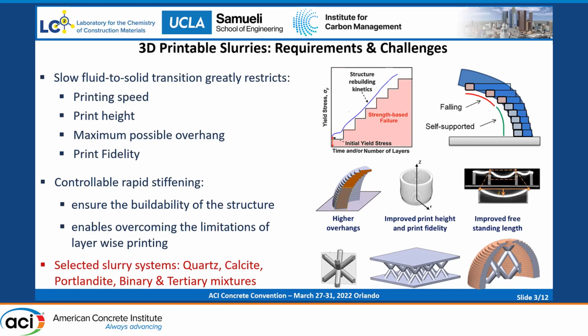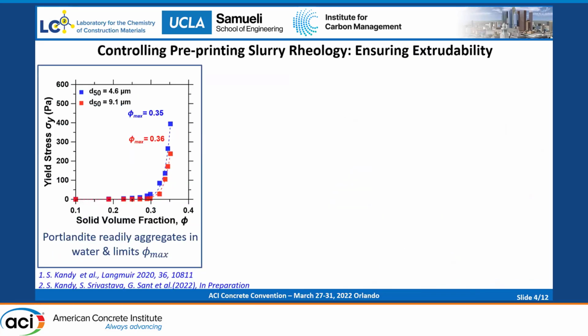We demonstrated it on suspensions like quartz, which is an inert suspension, calcite, which is one of the most commonly used structural materials, and portlandite. Portlandite is a material that we selected because it is an example of a high ionic strength and high alkaline suspension. We also demonstrated it for suspensions which are binary and tertiary mixtures of these minerals. But we can extend this approach to any minerals, including ordinary Portland cement. So how did we do that?